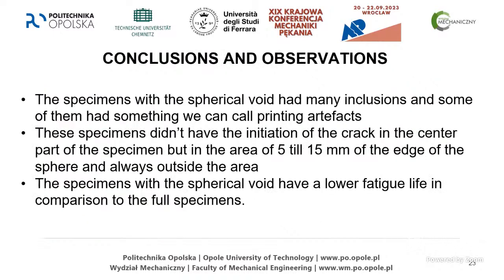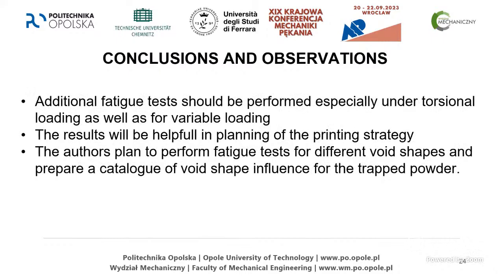Okay. As for the conclusions and observations, the specimens with the spherical void had many inclusions, and some of them had something we can call printing artifacts. These specimens didn't have the crack initiation in the center part of the specimens, but in the area of 5 to 15 mm from the edge of the sphere, and always outside the area. The specimens with the spherical void have a lower fatigue life in comparison to the full specimens, as expected.